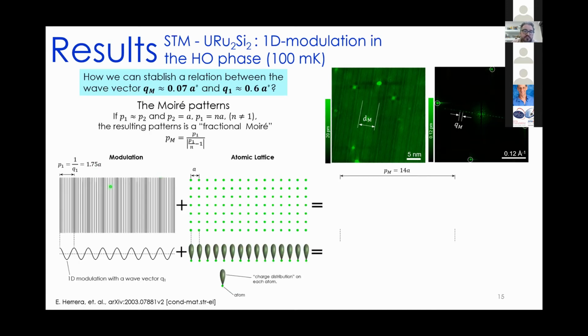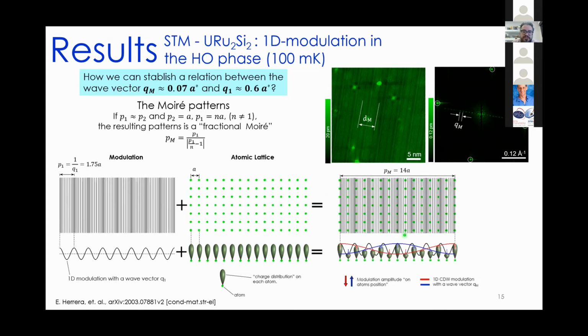So let me show you here the model that we propose. Here we have a one-dimensional modulation, with a periodicity related to the vector Q1. And here we represent the atomic lattice with these green dots. So this is the top view, and this is a lateral view of the model. Here we model the atomic orbitals on each atom with these lobes, and the lobes represent the charge distribution on each atom. So the overlapping of the modulation and the atomic lattice results in this pattern.